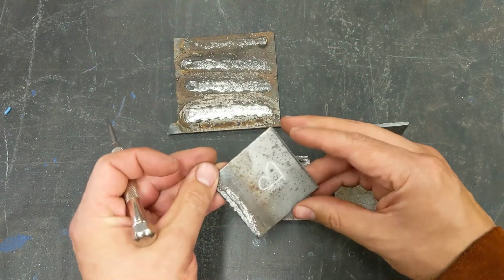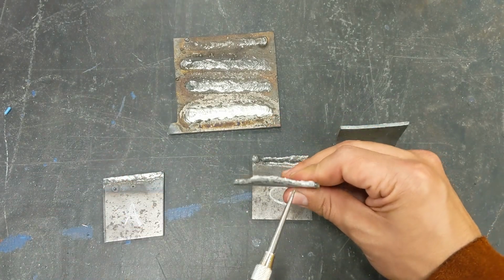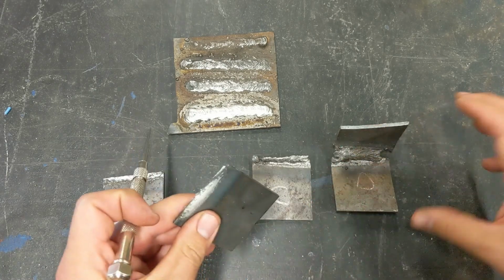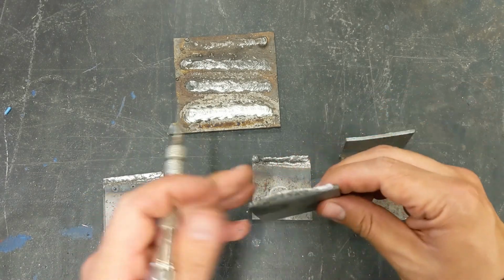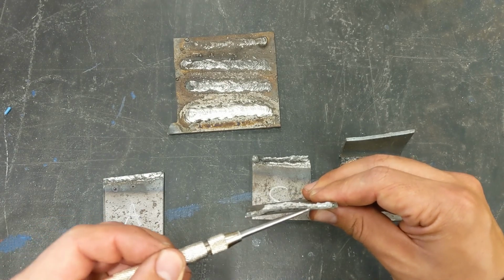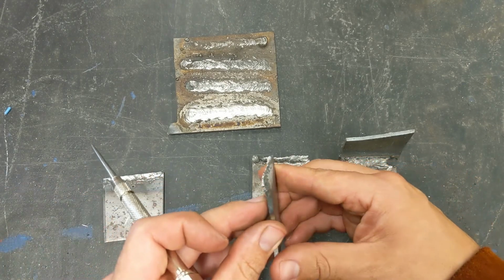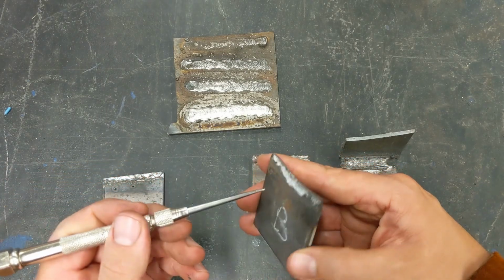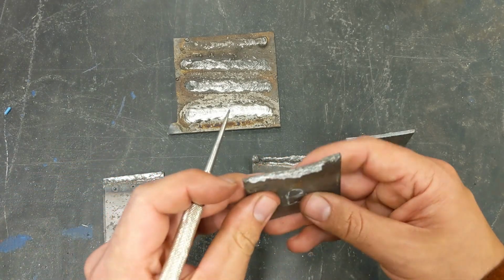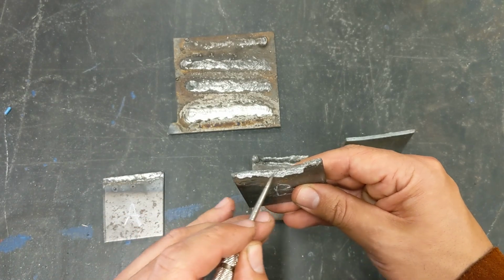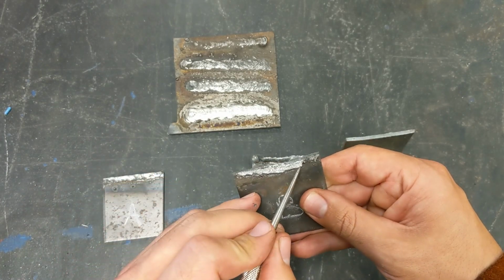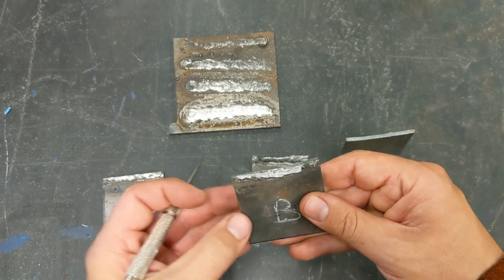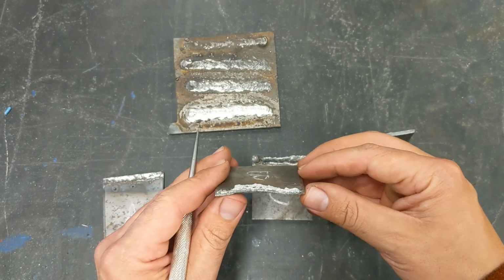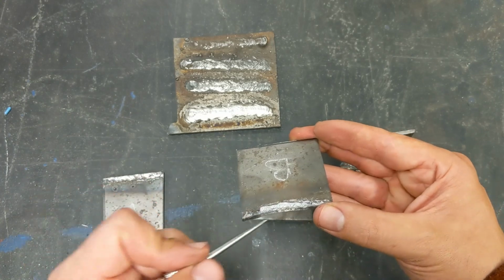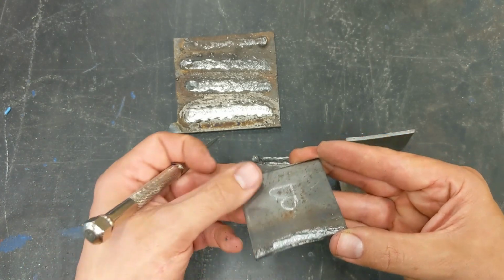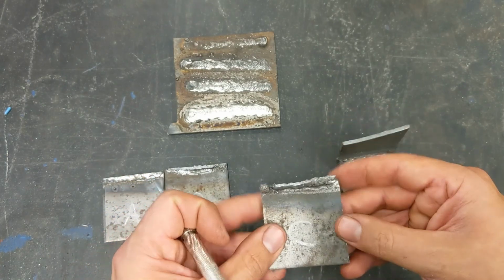Here, when we look at sample B, we can see that when the sample bent to break, you bend them like so, it actually pulled some of the base metal up, so there was some deformation. It tried to pull the weld all the way over, but it still broke, and again, it broke because there just wasn't enough weld penetration inside. A little bit more weld cross-section, the added amperage gave the electrode a little bit more energy to transfer some material down onto the workpiece, but still a failure.